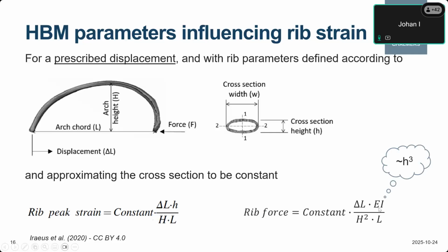On the other hand, the rib force is proportional to Young's modulus, so here we only consider small deformations. So here we have the material, and here we again have the height of the cross-section, but cubed. And then we have the global parameters. So the force, and therefore the stiffness of the rib, is dependent on the material. But for a prescribed displacement, the material does not affect the peak strain.